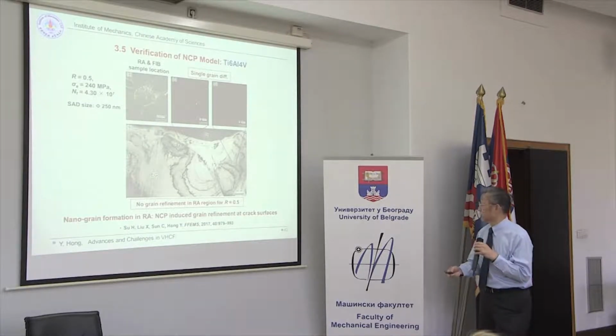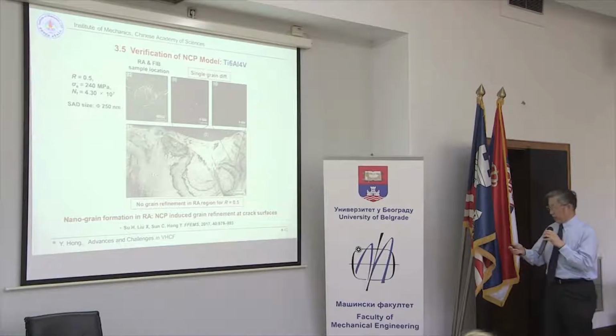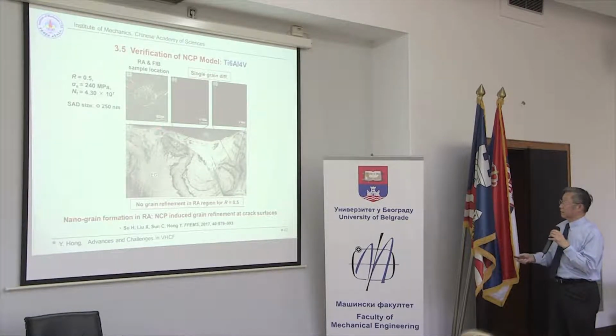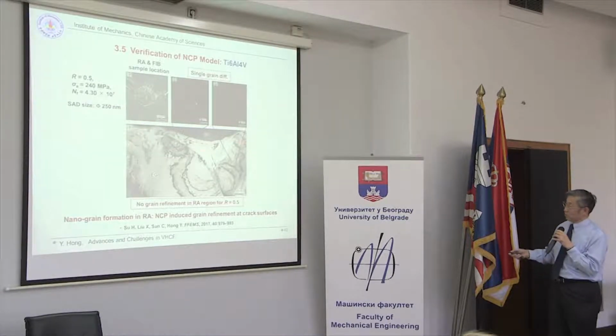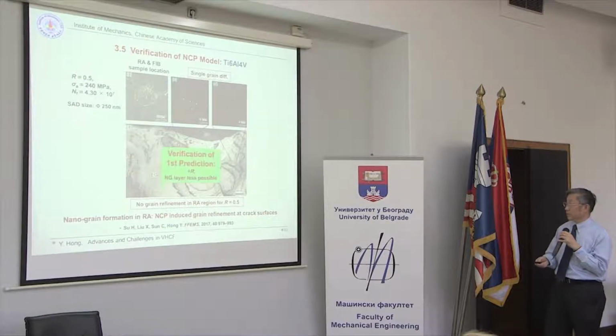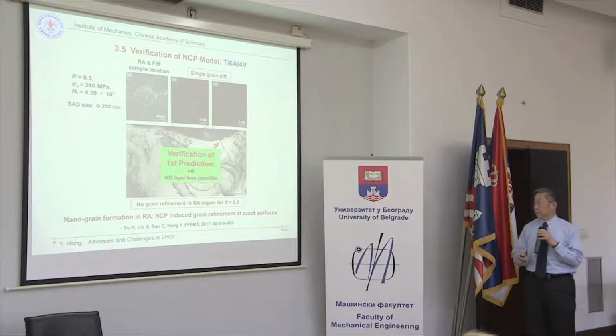Okay. For titanium alloy, we also performed the observation of tests with 0.5 stress ratio, and we observed the fracture initial region, and we may see a very nice microstructure just underneath the fracture surface without microstructure refinement, and the diffraction pattern shows isolated spots, coarse grains. And this is also a verification of the first prediction.